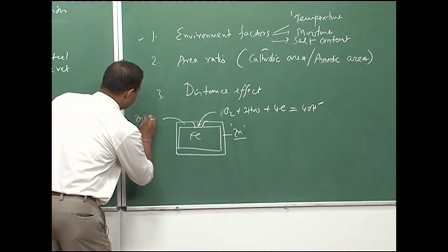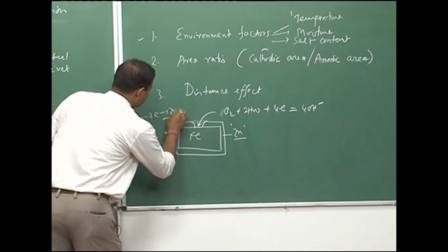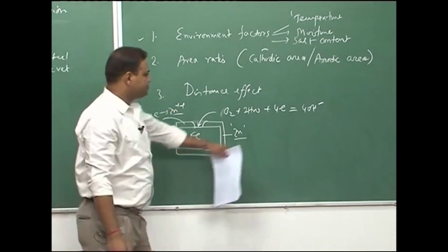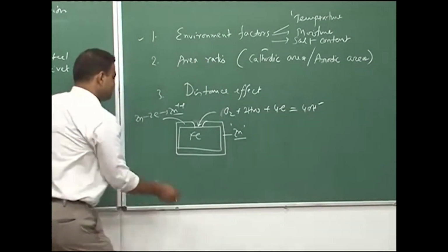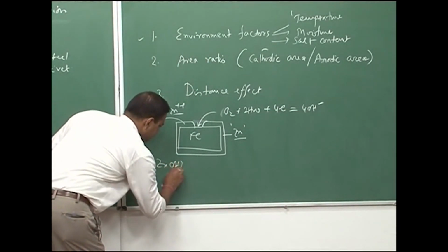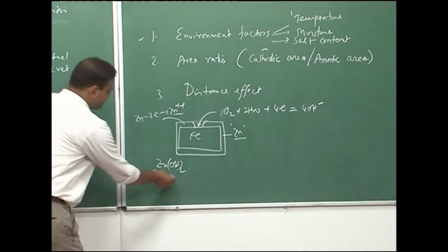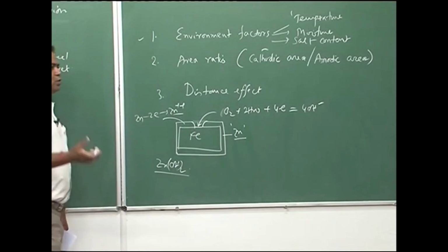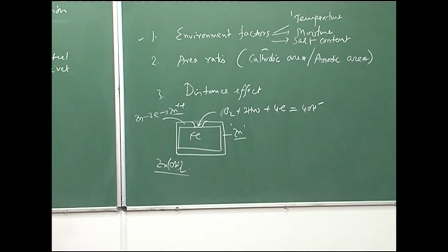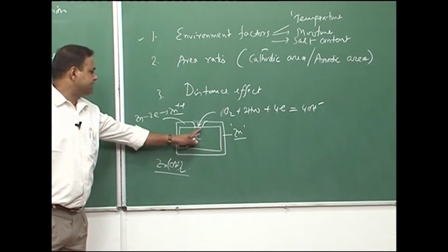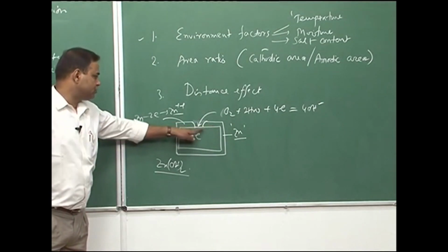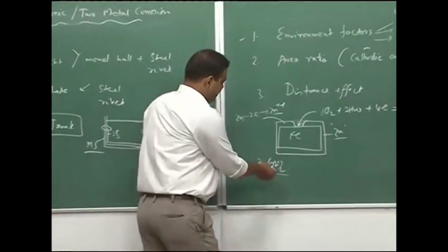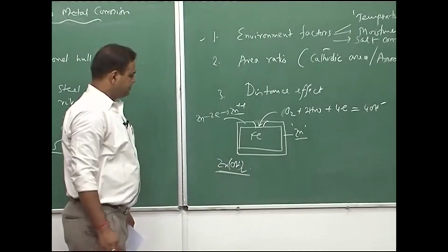Since it is anodic, there would be zinc corrosion, and this Zn2+ will react with OH- and form zinc hydroxide. Zinc hydroxide forms on the surface as a loose powder, and the iron still acts as cathode and the zinc as anode, so the iron will be cathodically protected. So, we see that zinc hydroxide is forming.